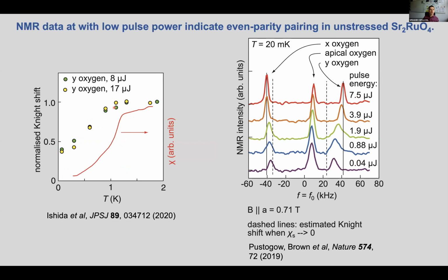Kenji Ishida from the University of Kyoto has also done this experiment. He was able to raise the temperature to above Tc. So here he shows Knight shift versus temperature, and there's a strong reduction in Knight shift as the sample becomes superconducting.